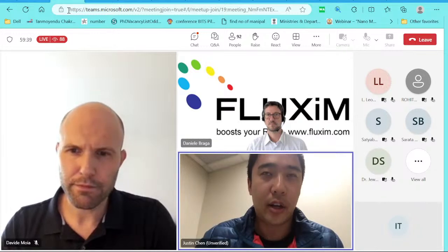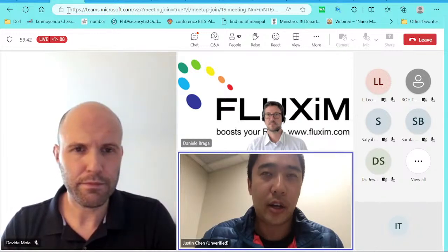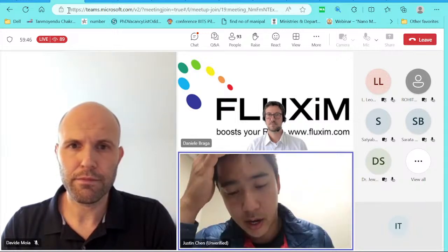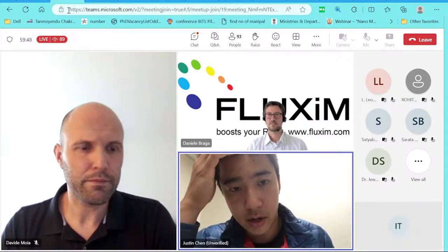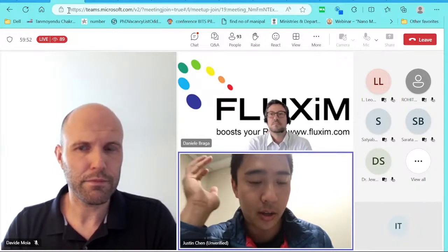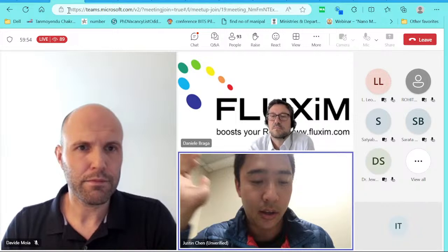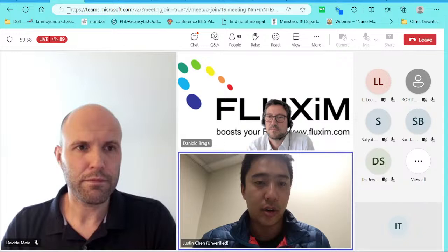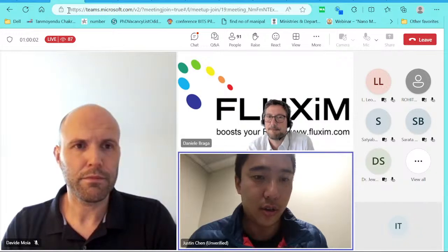And the concentration is about 1.5 molar, so it's quite thick. And I think a lot of people who are achieving the higher efficiencies now are using a much higher concentration, because you can get something about 800 nanometers of perovskite, and that will really help boost your current. But of course, the fill factor can be difficult to also keep high at the same time.